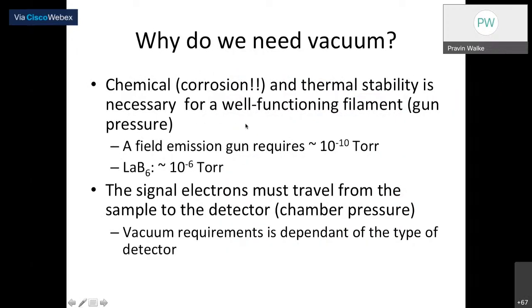So sometimes people will be worried about why electron microscopy needs a vacuum, right? Because electron microscopy without vacuum is not possible. And why do we need a vacuum? Because in a normal optical microscope we are not using any vacuum, right? So why in an electron microscope do we have to use the vacuum? First of all, chemical corrosion should not happen, environmental issues. Secondly, the thermal stability, which is very necessary for well functioning of your filament or gun pressure. So your gun pressure is very important to extract the electrons.